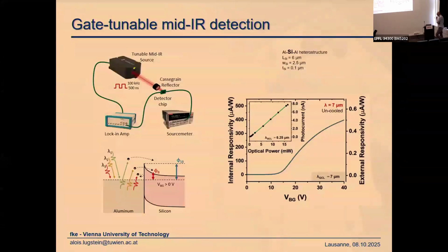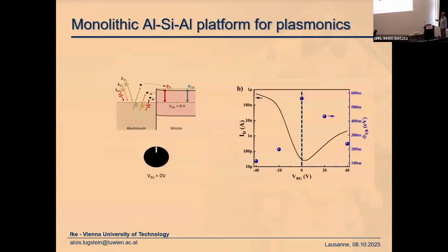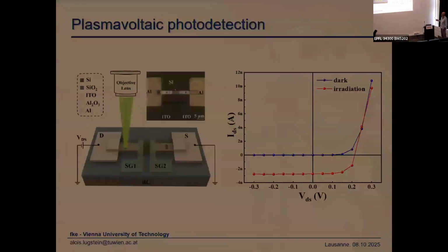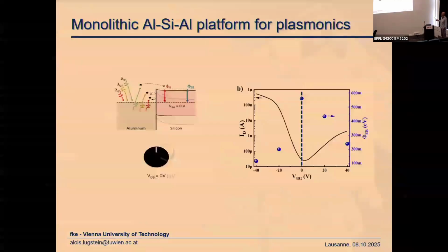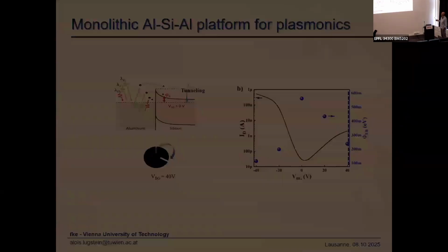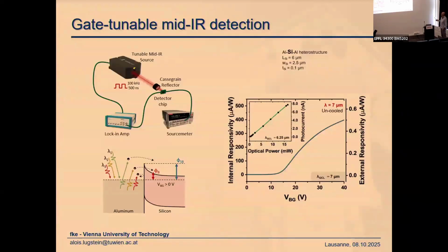And a postdoc of mine, Mauro, is working on this mid-infrared detection scheme. He investigated a 7 micrometer laser. The only thing he did is, it's the very same device that we used for the green laser experiment. And he changed the gate voltage, and you see that if you are above 15 volts, you get a nice signal out from a 7 micrometer laser. It's linearly dependent on the power of the exciting laser.